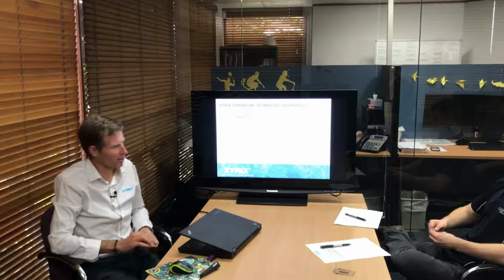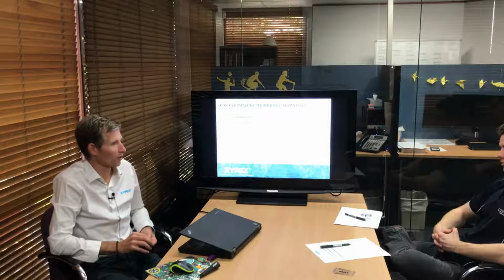One of the things we do have is testing that has shown we seal cracks above 0.4 mil. I think we've got a test report which shows we've healed and sealed a crack up to 1 mil under a head of pressure after 70 days. But ultimately, we guarantee with project specific conditions that it's going to be 0.4 mil.